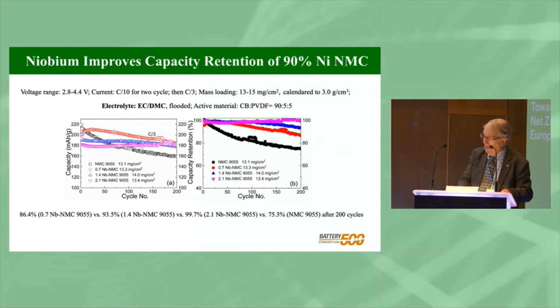So what effect does the niobium have? Mostly positive, but not all positive. So here we have our capacity. So you now see our capacity is holding pretty well, but this is the one with the highest capacity. This is about 0.7 niobium in it. As we put more and more niobium in this case, we're losing initial capacity, but we're maintaining the capacity. So here's the niobium free. It loses capacity continuously. So clearly niobium is stabilizing the lattice.